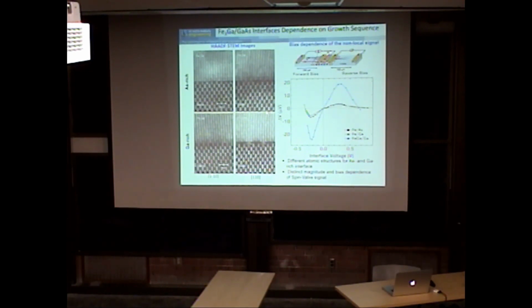And in fact, you can look more carefully. Do you notice this? There's something funny there. That, we believe, is the remnant of the c(8x2) gallium-rich surface of gallium arsenide before we put the iron 3 gallium down. But if I look at our spin signal as a function of bias, you see virtually nothing for the arsenic-rich interfaces. And we saw a nice signal when you had the gallium-rich interface. So this is telling us that the interface is very important for the spin injection and the spin transport.